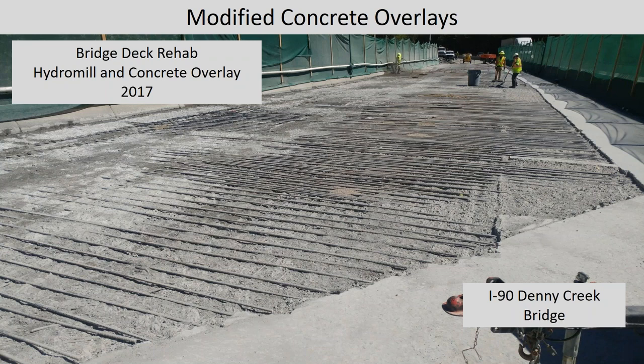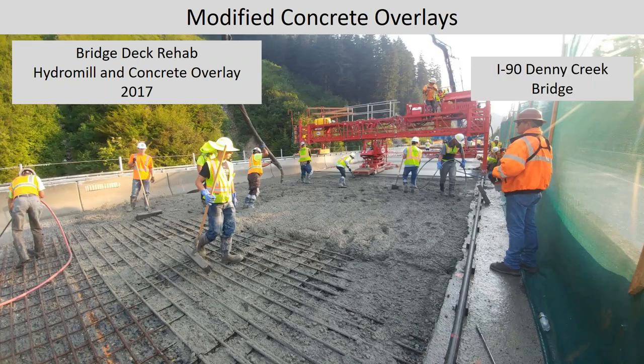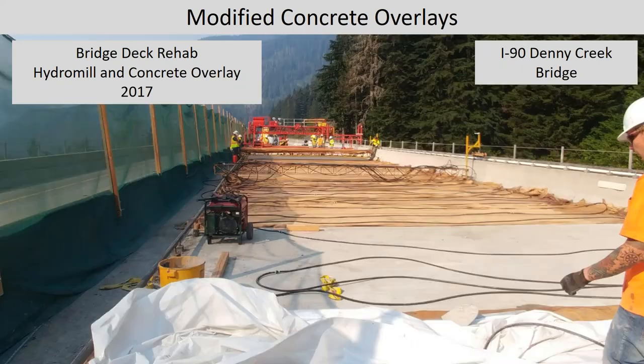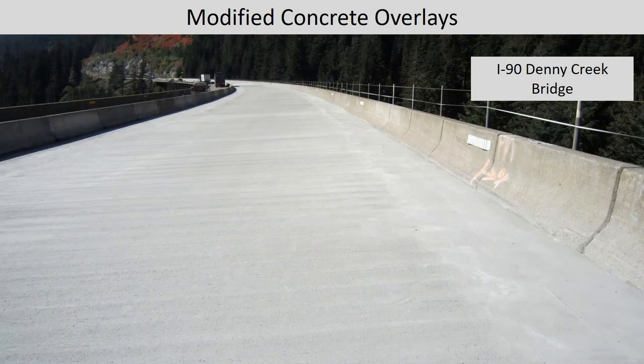We did it in two stages, 2017, 2018. First we hydromilled the deck, got some of the concrete overlay off, and then some of the original concrete off. And then we went back in with the concrete overlay. And same curing that Anthony kind of showed you, wet burlap. And then here's the final surface before they did the longitudinal grinding. So if you ever get a chance, you can see what that bridge looks like today.